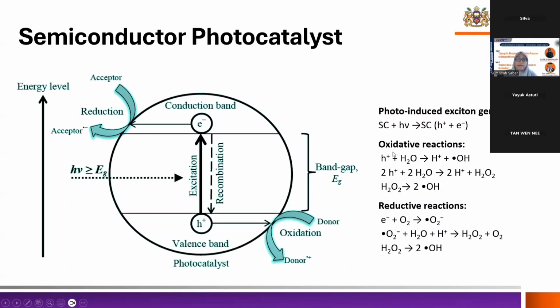And then at the valence band here, it would undergo oxidation reaction, which in the end will produce hydroxyl radical. And then at the conduction band, it will undergo reduction reaction to produce also the hydroxyl radical. So in this case, there are a few oxidative radicals being formed, such as hydroxyl radicals and superoxide radicals that are highly oxidizing and can mineralize organic pollutants into CO2 and water.